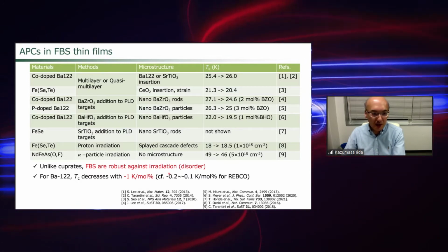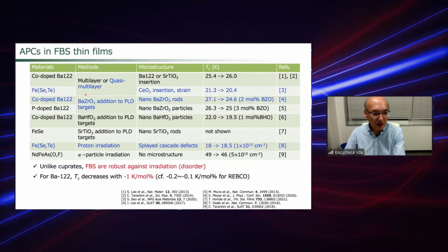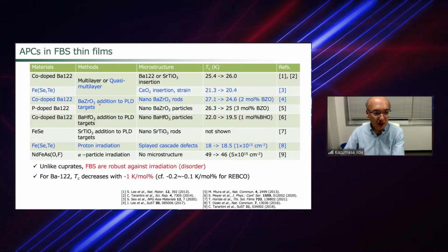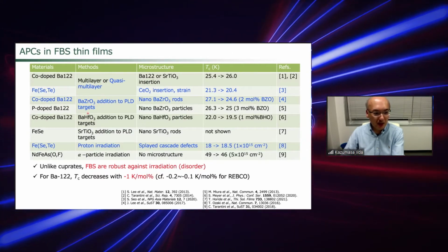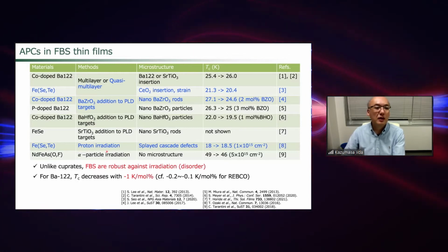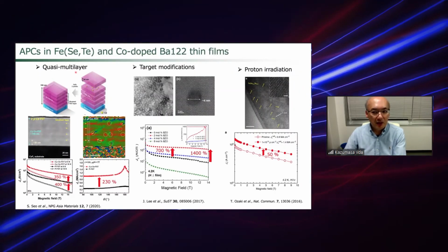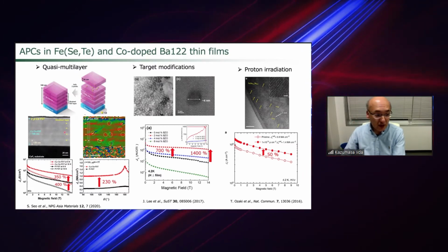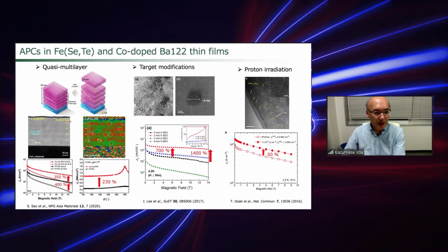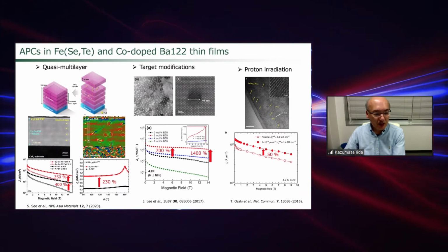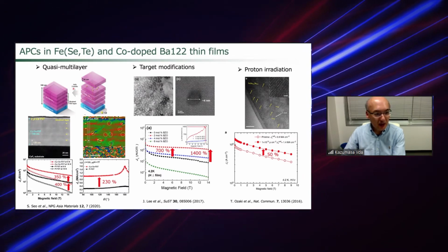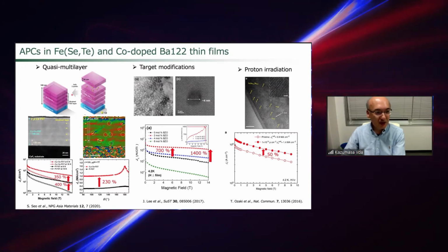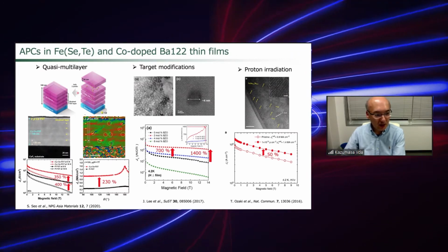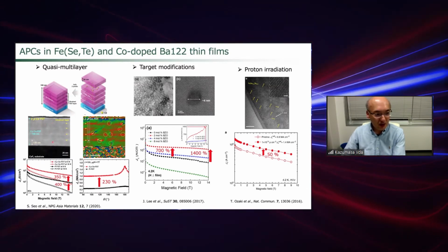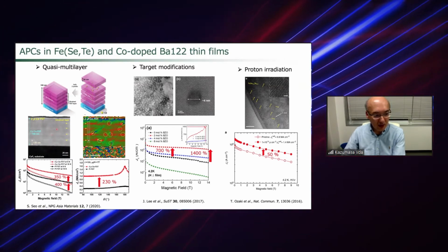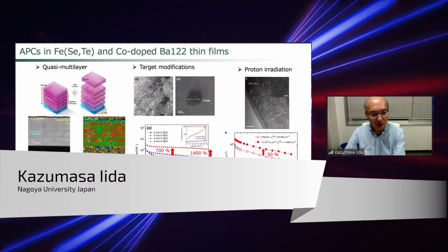And for the next slide, I will show you some examples. Here, the quasi-multi-layer approach, the barium zirconate addition to the PLD target, and the proton irradiations. Okay, the first one is the quasi-multi-layer approach. Seo et al. made a quasi-multi-layer using iron selenium telluride and strontium titanate, and they deposited only 2 pulses in between the selenium oxide. And here is a cross-sectional TEM image of such a quasi-multi-layer and the corresponding strain mapping of these materials.